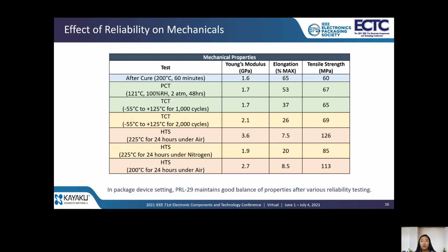And then it's important to have a good understanding of how the material will behave after reliability testing. So I've tabulated the mechanical properties of PRL-29 after PCT, thermal cycling, and high temperature stability in comparison to the baseline after being cured at 200 degrees C for an hour. After PCT and TCT for 1,000 cycles, the material properties don't change significantly. I would even argue that TCT for 2,000 cycles isn't super significant either.